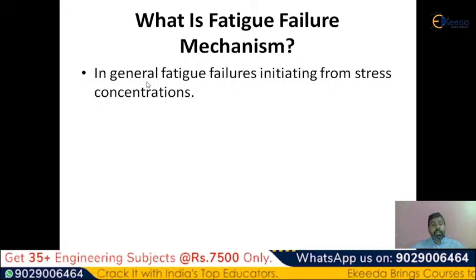I repeat, whatever the fatigue failures that you are observing in the material, if you want to reduce the fatigue failure mechanisms, you cannot completely avoid the fatigue failure, but you can reduce the fatigue failure. Here, wherever the stress concentration areas exist in the material, you have to avoid those stress concentration areas. So that means which are the starting points of the fatigue failure. Whenever the stress concentration areas are observed in the material, automatically the fatigue failure will start. That means the fatigue crack will start from those points at which the stress concentration exists.